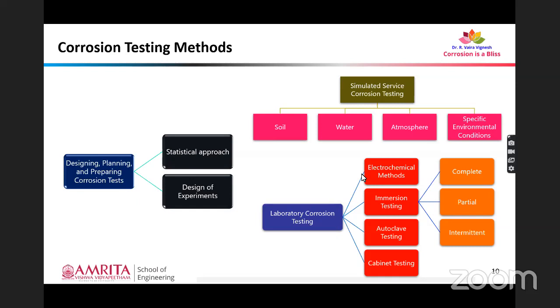Let's say, for example, if you want to test the material's capability in a marine environment, in simulated service corrosion testing, we just take the specimen to the marine area itself. For example, a seashore, we do the corrosion testing there. We keep the specimen hanging there for a few days or few months or few years, then we analyze the corrosion phenomenon. But if it is laboratory based corrosion testing, we create a solution that mimics seawater. For example, 3.5% sodium chloride is always considered as simulated seawater. So that can be used for laboratory corrosion testing methods.